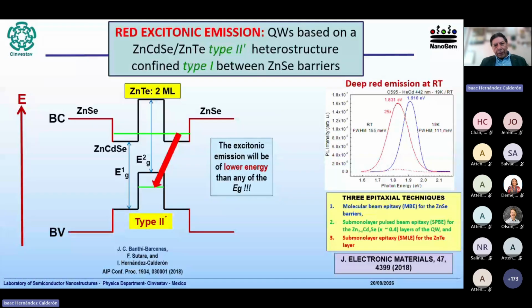And additionally, with a more sophisticated band gap engineering, we can produce a type 2 heterostructure confined type 1 between zinc selenide barriers. And with this type of band gap engineering, we can produce deep emission at room temperature. And for the production of this heterostructure, we use 2 different epitaxial techniques, MBE and SMLE. So this is just an example of things we are doing in our group.